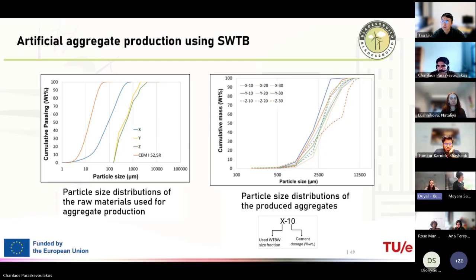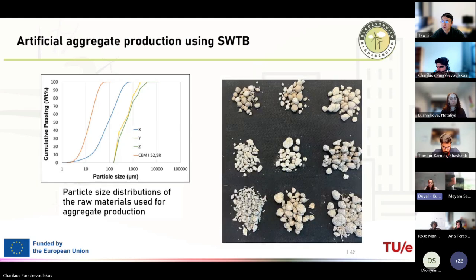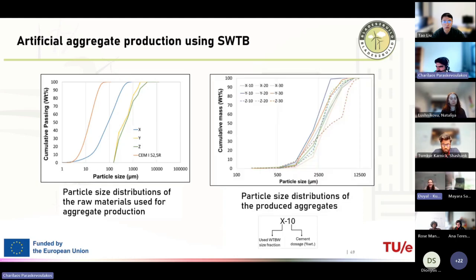This is the particle size distribution of the raw material. As I mentioned, different size fractions were used for the aggregate production, which are X, Y, and Z, and also the cement. And this is the particle size distribution of the produced aggregates, with the abbreviation of the size fraction of waste and the dosage of the cement.